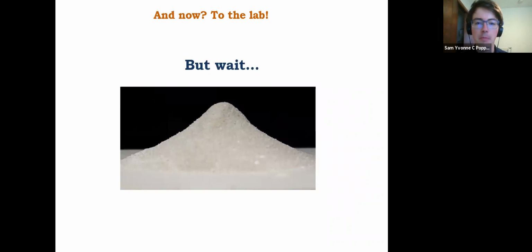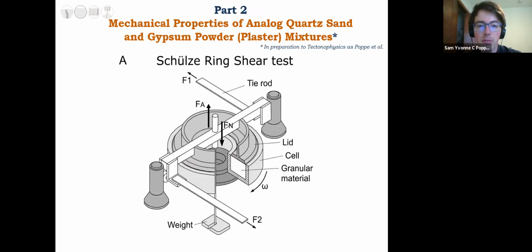Because in the lab in Brussels at the VUB, we traditionally used granular mixtures of sand and plaster in the experiments. And we got wondering, do we really understand the rheology, the mechanical behavior of such mixtures? And it turned out no. So we did a range of tests, material tests, and this is a paper in preparation to submit to Tectonophysics as soon as possible, I hope. The current stay-at-home situation has set everyone's work back a bit, I guess.